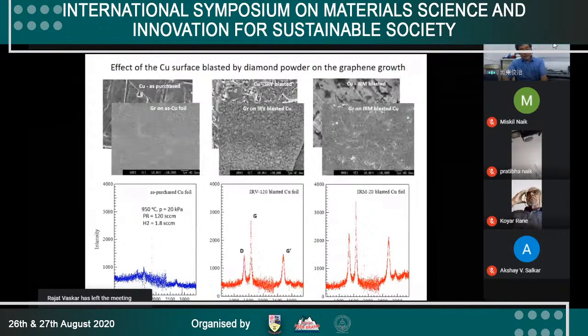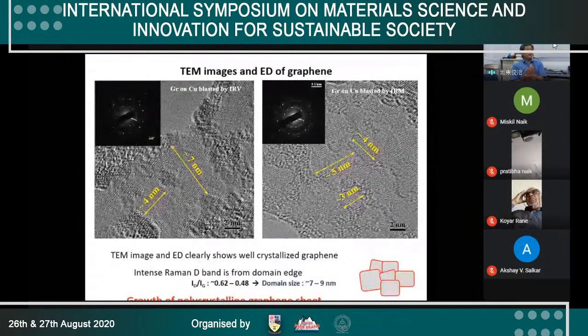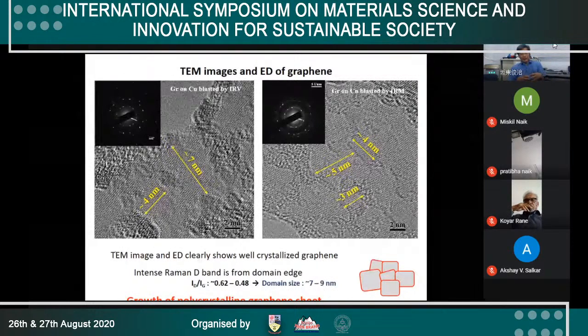Next, this is the transmission electron microscopy. After removing the graphene from the copper foil, we took a look with high resolution transmission electron microscopy. In such a case, we can see a small domain size of the graphene grown on the copper foil. You can see in the bottom schematic the growth of polycrystalline graphene sheet. We can get this from the uniformly rough surfaced copper foil, and the reproducibility becomes so high. Okay, this is the result of the graphene growth.